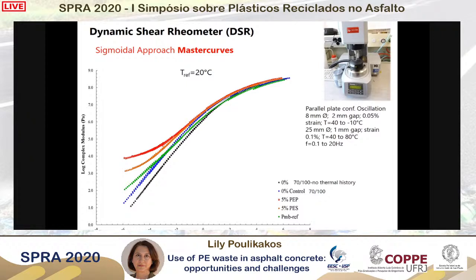Well, first of all, in the high frequency, low temperature regime on the right-hand side of the curve, we don't see a significant difference. However, on the low frequency, high temperature end of the curves, we see a significant difference between the plastic blends and the other materials. This could be an indication that we have the potential to improve the rutting resistance or the performance at high temperatures. Well, I want you to keep this in mind